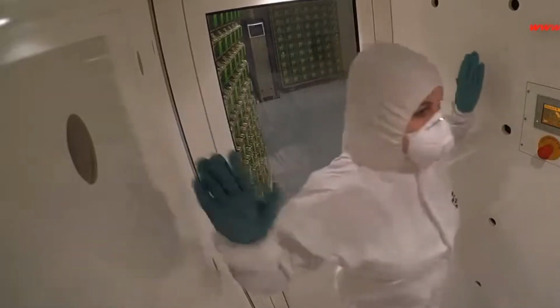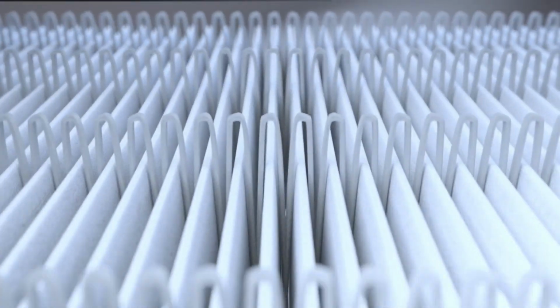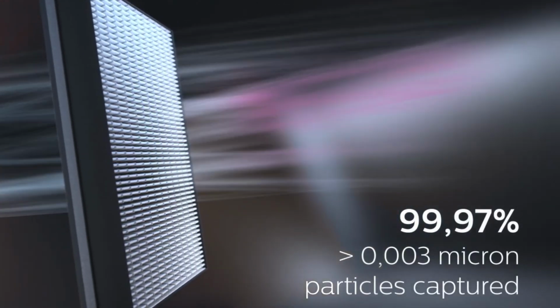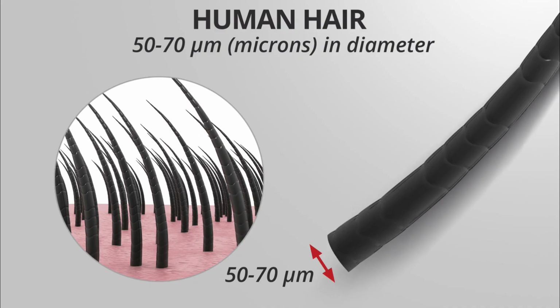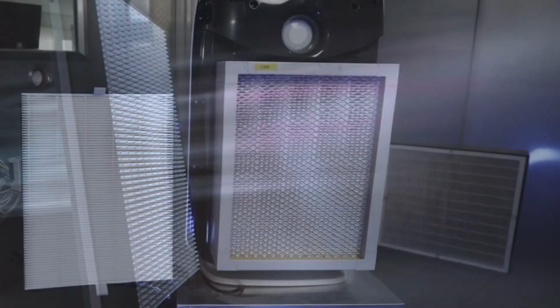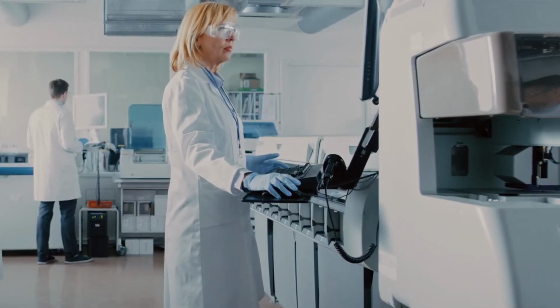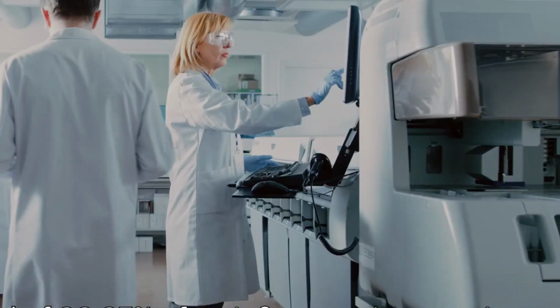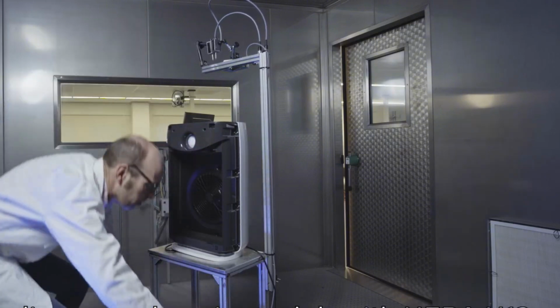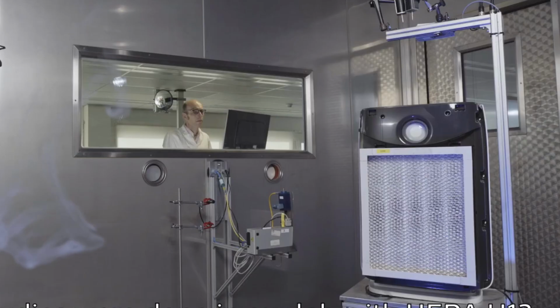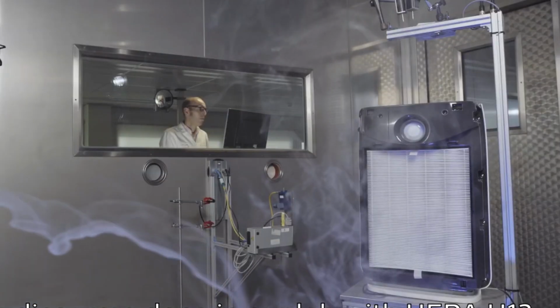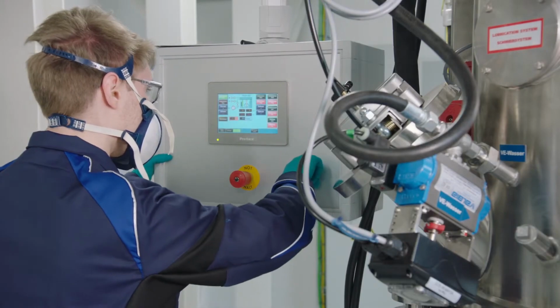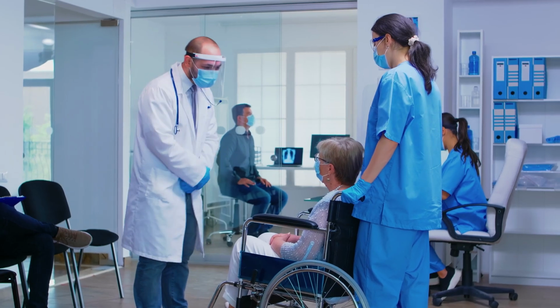The air inside is filtered through high-efficiency particulate air, HEPA, filters, which capture 99.97% of particles as small as 0.3 microns. For context, a human hair is about 70 microns thick. The air pressure in the clean room is also carefully controlled to ensure that contaminants from adjacent areas don't seep in. This level of environmental control is essential because even a single particle of dust can create a defect in the coating, leading to a weak spot in the battery that could fail under stress. So workers suit up in clean room gear, and the air is filtered cleaner than a hospital ICU.